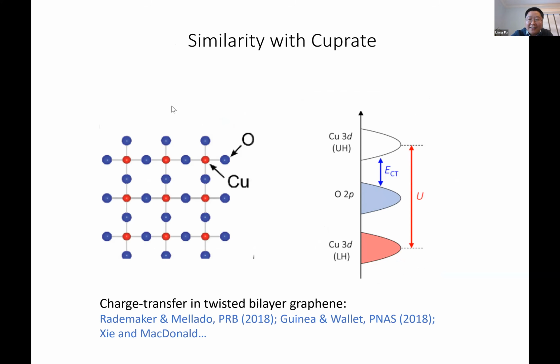Also let me mention that this charge transfer insulating state has been discussed a lot in the context of cuprates. In cuprates, there are copper and oxygen atoms. They are the analog of what I call cations and anions. And again, in this case, because of the large on-site repulsion associated with the copper d orbitals, doped holes prefer to go to the oxygen site. So the energy gap to charge excitations is a charge transfer gap rather than the Hubbard U. Also, I want to mention that this charge transfer effect has also been discussed in the context of twisted bilayer graphene by these people. These are some inspiration for our work.